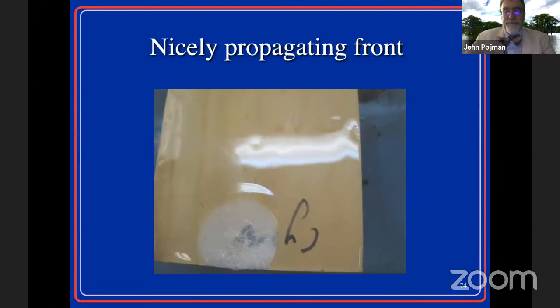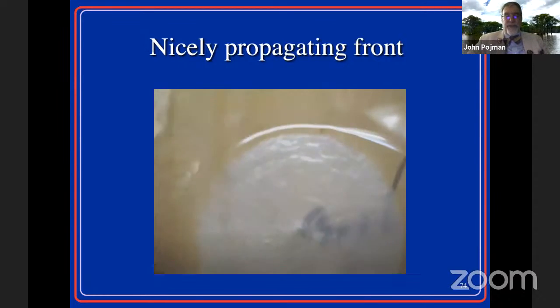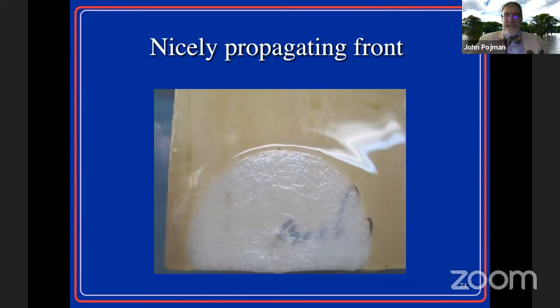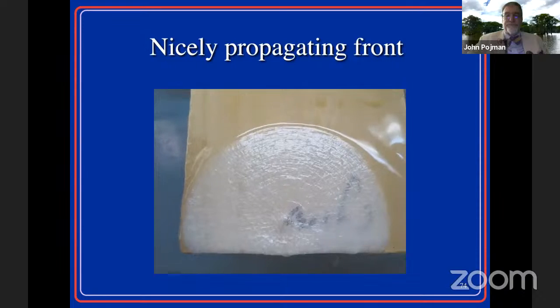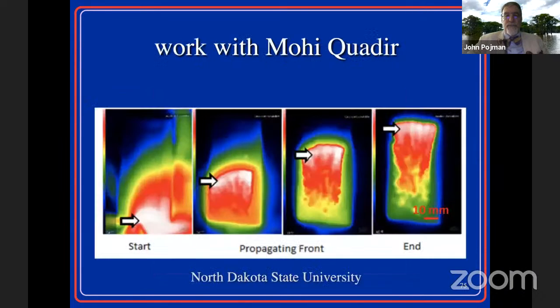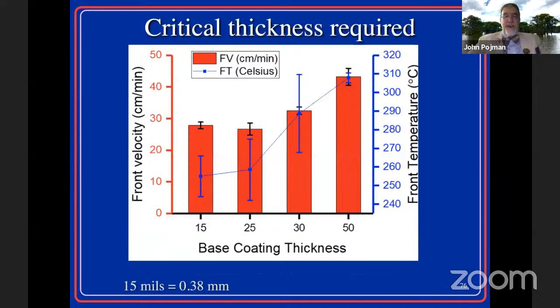So here's an early experiment I did myself 10 years ago. And we can see that we get this self-propagating reaction. So we started working with North Dakota State University, which has a long history working in coatings, to develop true coatings, not these couple-millimeter-thick layers, but real coatings, carefully controlled, and then be able to analyze their properties. This was done imaging with an infrared camera. The coating thickness is in something called mils. If you had something that was, say, 0.4 millimeters, pretty thin, we could get fronts that still propagate pretty fast and get pretty high front temperatures.